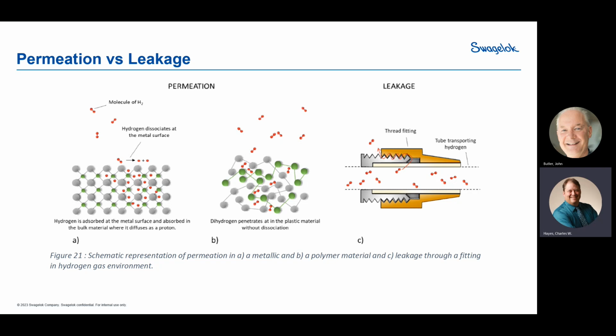Now, when it comes to rubber materials, as we use them for O-rings and so forth, it's very important that they go through O-ring testing. Those materials need to be tested and qualified for use in hydrogen. Sometimes they shrink, sometimes they get bigger, sometimes up to 70% larger due to swell from the hydrogen, because so much goes in there and hangs out. When you think about O-rings in a sealing area, usually that seal area doesn't have enough room for an O-ring to grow by 70%. So it falls in the category of bad things happen from an engineering standpoint.